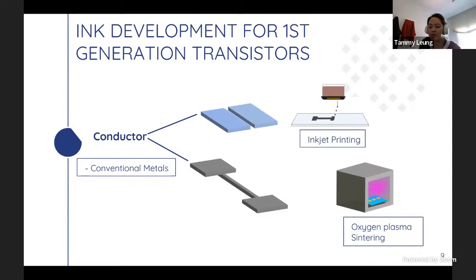Inkjet printing was chosen here because it has the ability to deposit different types of inks and metals onto the surface. And the addition of plasma allows for lower sintering temperatures as compared to thermal heating techniques. In this case, we specifically chose oxygen plasma for the sintering process because this can be found in a standard laboratory and does not require things such as high vacuum to operate. So it operates at atmospheric pressure.